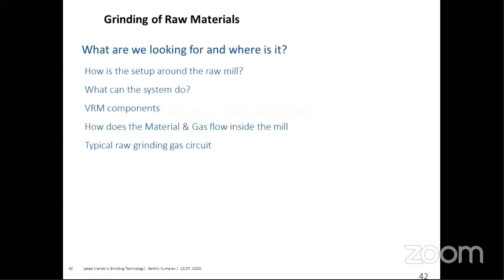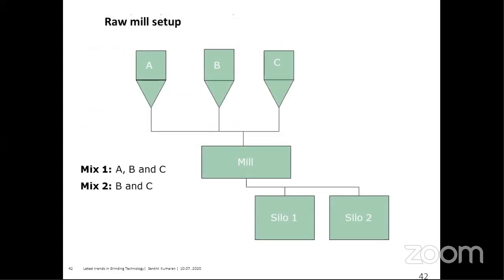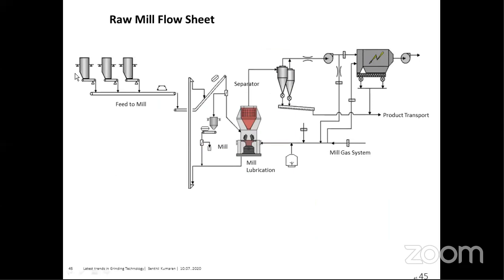Okay. So the grinding of raw material, when we see, here we have 3 or 4 types of material. It has to be ground using the mill, and then it will be stored in the silo or in different silos. So this is a typical raw mill flow sheet. These are all bins, and we monitor and weigh all this quantity, and then we feed to the mill. This small arrangement is a metal detector. If there is any metal inside this system, it detects the metal, separates it out, and it is taken out through reject.